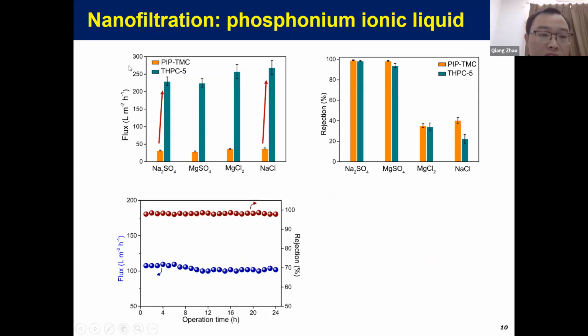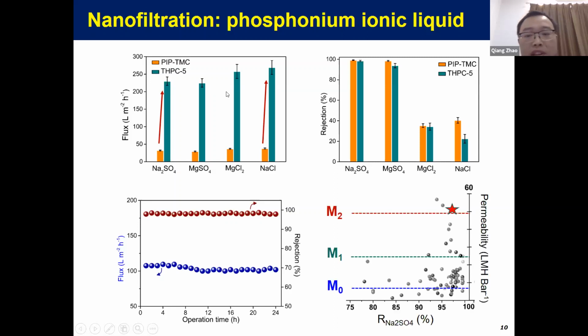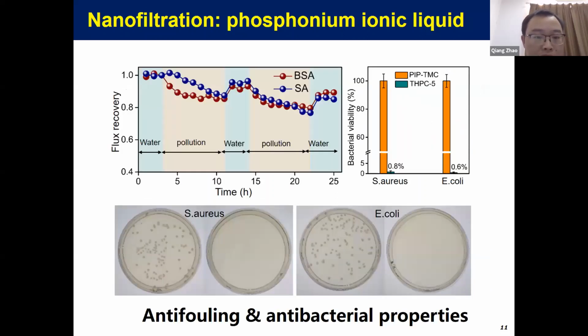The most important feature, as you can see from this column, the blue bar, is that the flux was improved by more than 7 times. It is also noteworthy that the permeability is stable versus the operation time at a relatively moderate pressure of 2 bar. If you compare this permeability with state-of-the-art membranes, you will see it is among the top, the most permeable membranes in the literature, although the others may be two-dimensional membranes.